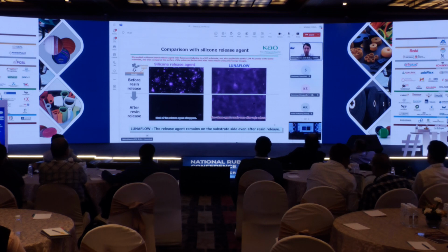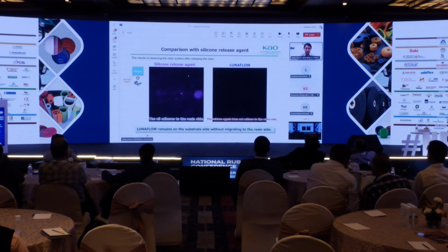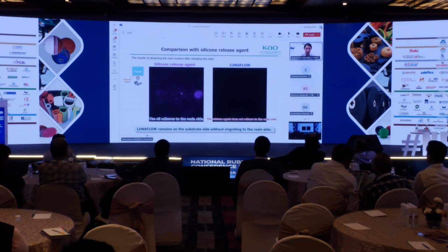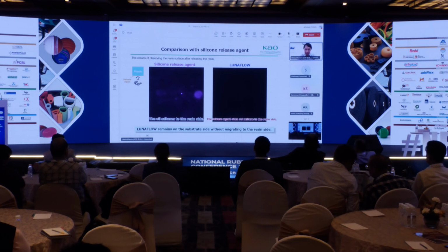This is also a benefit. This is the result of observing the resin surface side after releasing the resin. Comparing with the conventional silicone release agent, LunaFlow doesn't adhere to the resin side like this. It means LunaFlow remains on the substrate side without migrating to the resin side. This is also a benefit of this agent.